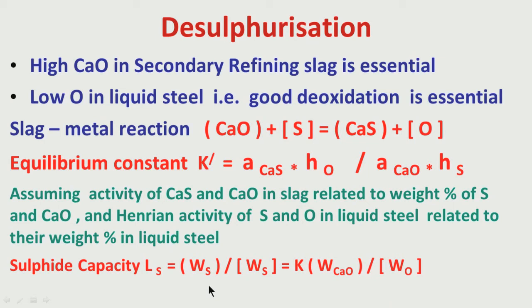WS is the wt of sulfur present as calcium sulfide in slag, because the reaction is calcium oxide in slag reacting with sulfur in liquid steel to generate calcium sulfide in slag and oxygen in liquid steel. So, whatever sulfur was present in liquid steel, the idea is to transfer as much as possible from the liquid steel to slag as calcium sulfide. So, the weight of sulfur in calcium sulfide present in slag divided by the weight of sulfur in the liquid steel, that ratio is known as the sulfide capacity. The higher this ratio, the more sulfur in slag as calcium sulfide, the more the sulfide capacity, the better the desulfurization.